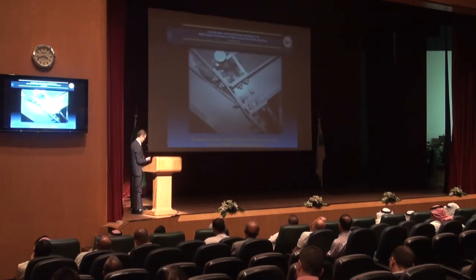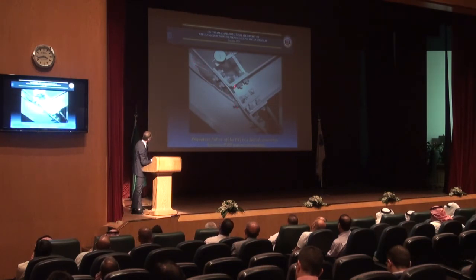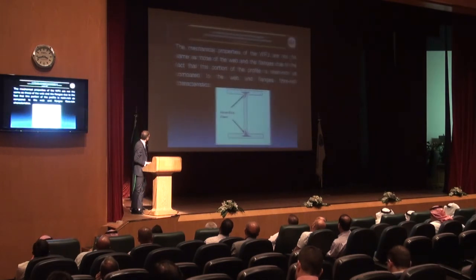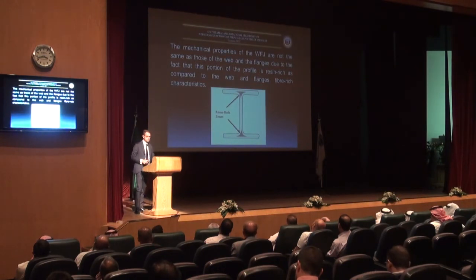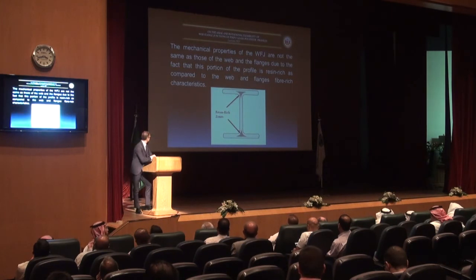This is a very important feature because this is a bolted joint. And as you can see, there is a separation between the web and the flange due to the insufficient fiber continuity in the profile. But the connection is safe. In fact, the mechanical properties of the junction are not the same as those of the web and the flange, due to the fact that this portion of the profile is, as we say, resin rich. In this web-flange junction, there is more resin than fiber. So this is a very critical point for the design